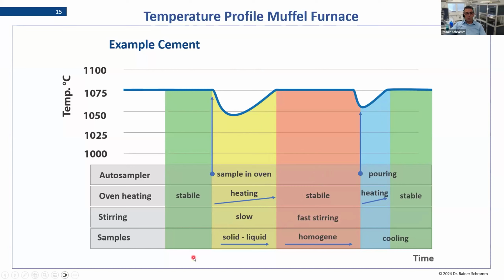And for the sample, if you look there, it is clear that here it is outside, it's solid. While it's then coming into the furnace, it gets liquid. And here you do the homogenization. And then afterwards outside, you cool to get a stable glass.